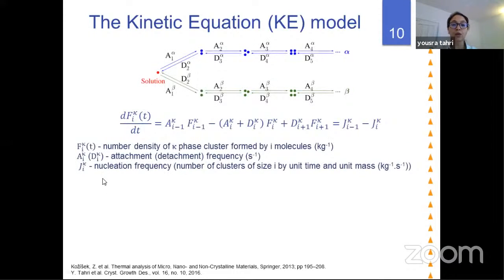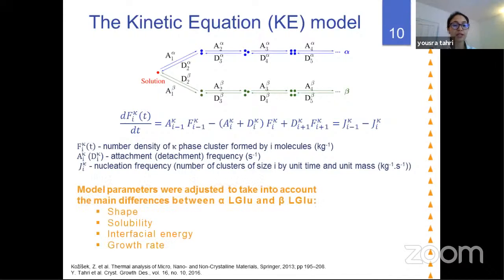We used the kinetic equation model. The kinetic equation model is based on attachment and detachment of monomers. We took into account in this model nucleation, growth, and ripening. The ripening mechanism is induced by the solubility dependence on size, which is the Gibbs-Thomson effect. So we wrote the kinetic equation for each polymorph, and we took into consideration the differences between the two polymorphs, which are mainly reflected in the shape, the solubility, the interfacial energy, and the growth rate.